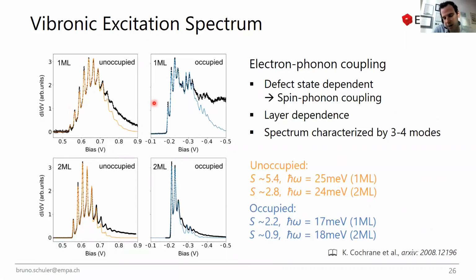What you're suggesting is essentially, can't we change the phonon occupation by changing the temperature? There are some limitations on what we can do experimentally. If you significantly want to change the phonon population or the thermal distribution, you would need to go to room temperature or so. Room temperature is about 25 milli-electron volts, and even then the change in population would not be that drastic, so it would be hard to see. Plus, working at room temperature and keeping atomic resolution is very, very difficult to do.